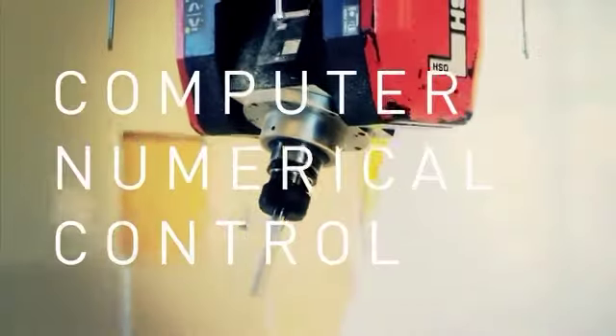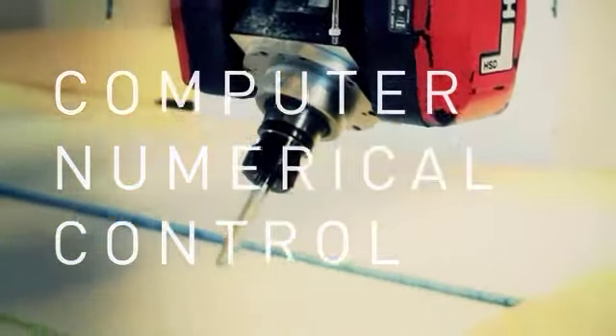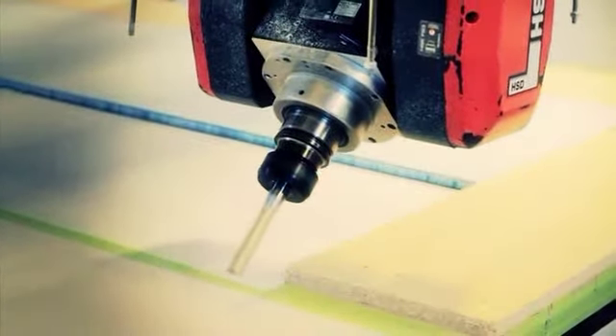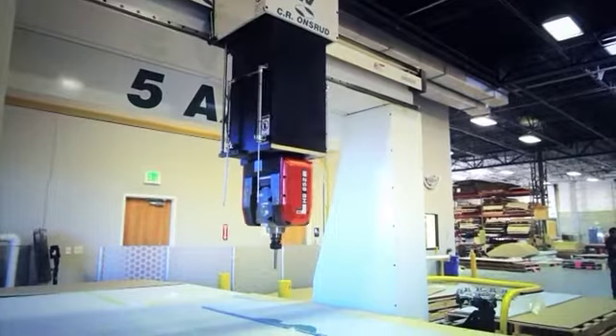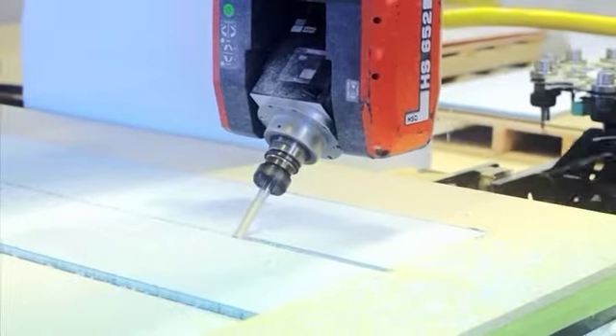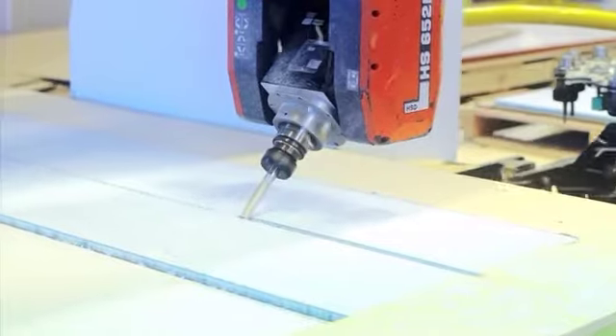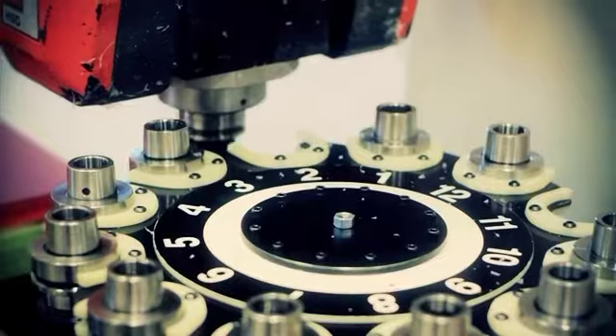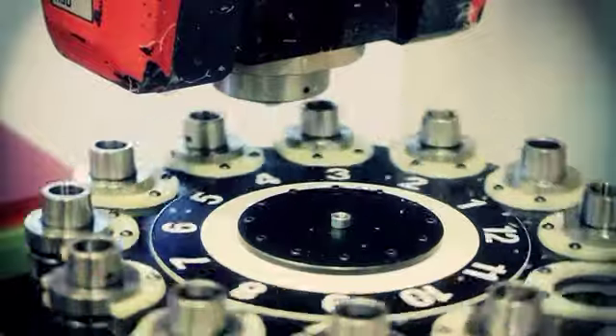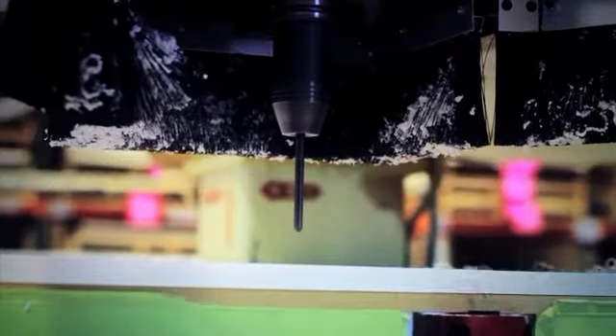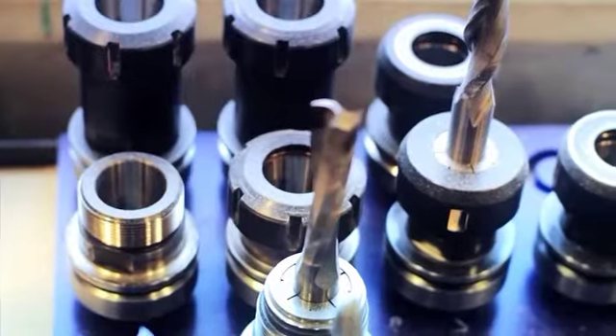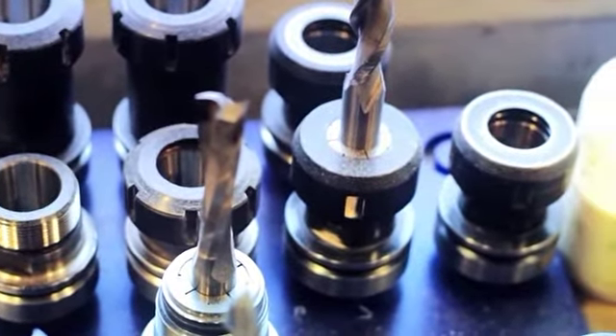Another common cutting method that is often employed with resin is that with a router, sometimes a hand router, or computer numerical control cutting, the CNC machine. This type of cutting lends itself very well to arcs, curves, and things that come to sharp, very high precision tolerances. The main consideration when looking at cutting with a router really involves what type of bit do you use. The best bit designs offer an upcut flute that will allow removal of the debris so as to prevent incidental melting of the material. These bit designs are widely available and very commonly used.